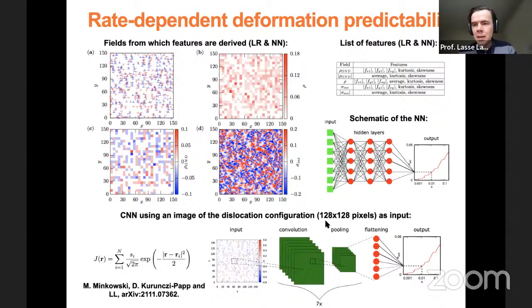by 128 pixels. And this is chosen because that's a high enough resolution that you can still resolve the individual dislocations as separate objects, but it's not so high as to make your CNN too complex, because if you have a very, very high resolution of your image, then you need to make your CNN more complex and you need more training data. So this is a compromise to still resolve the system, but not use excessive resolution.